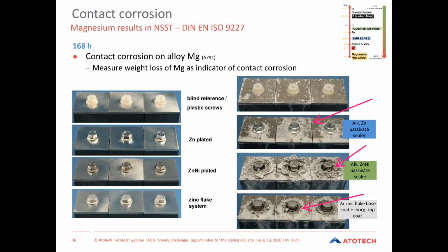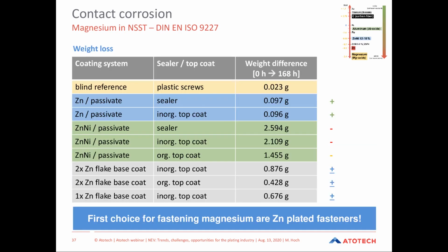And this is also illustrated when we look at the weight difference. In this table, you see on the left side the plating sequence: zinc plus passivate plus sealer, or zinc plus passivate and an inorganic top coat. Then in green, the zinc nickel plated parts, and in gray, the zinc flake systems. And in the right column, you see the weight difference. The blind reference had some weight difference, but it's 0.02 grams, so it's nothing. So there was no corrosion.